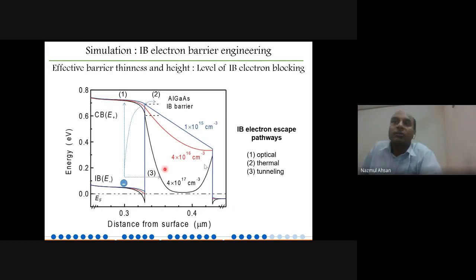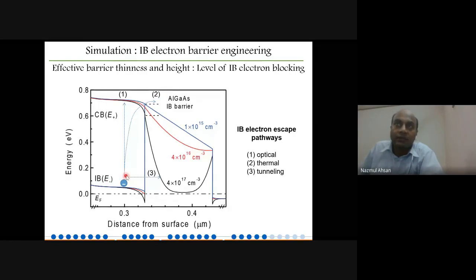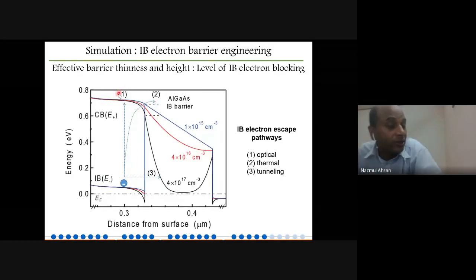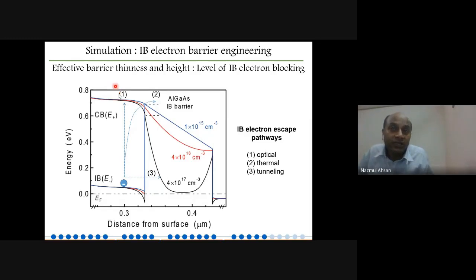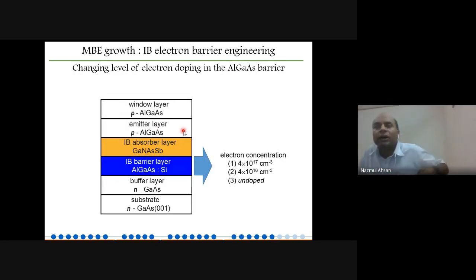This is the total summary: with a different doping profile in your barrier, if you have a high concentration, then electron tunneling will be high. But if you have lower concentration, you can reduce the electron tunneling. Then you are left with two options, either photon absorption or thermal escape. If you raise the band gap, you can reduce the thermal escape and are left with only one. In your gallium nitride arsenide, as I told you at the very beginning, if you change the nitrogen concentration, you can play with the band gap and also with processes 1 and 2, and you can optimize your device. This is the device engineering.